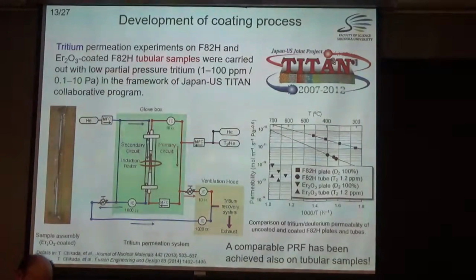Then we obtained that the coating on the tube sample is also good, as good as the plate substrate, the plate sample like this. So the comparable performance has also been achieved on the tubular sample. That's very good news.